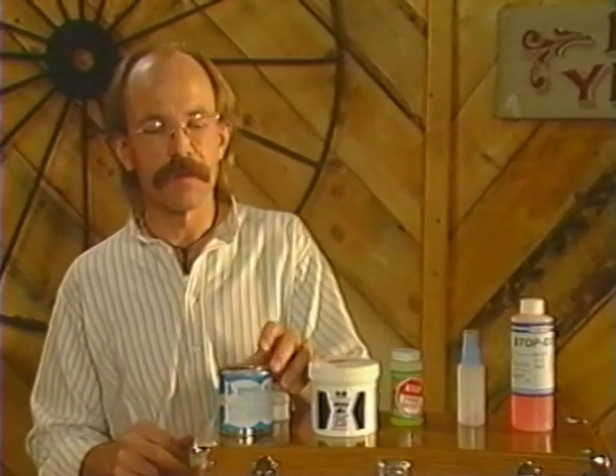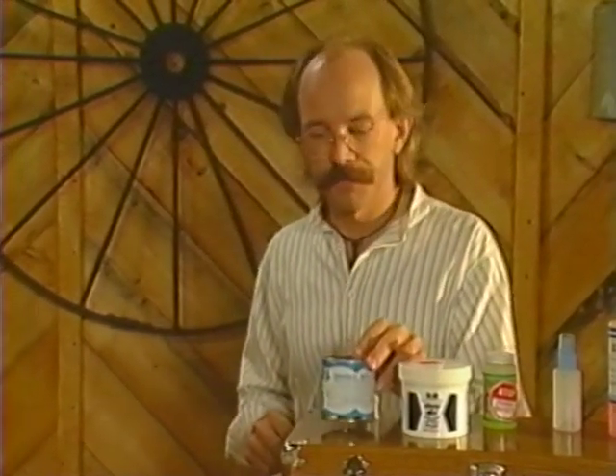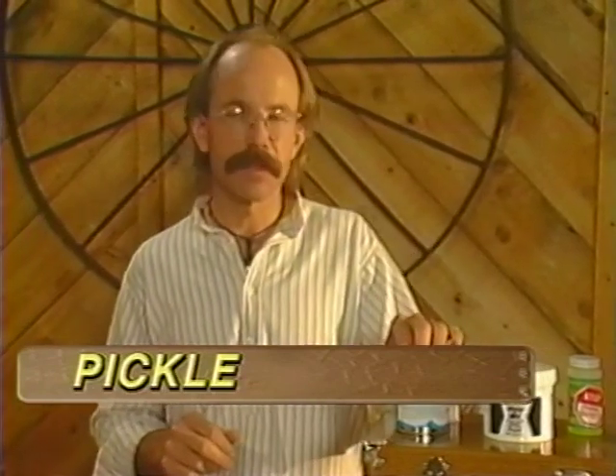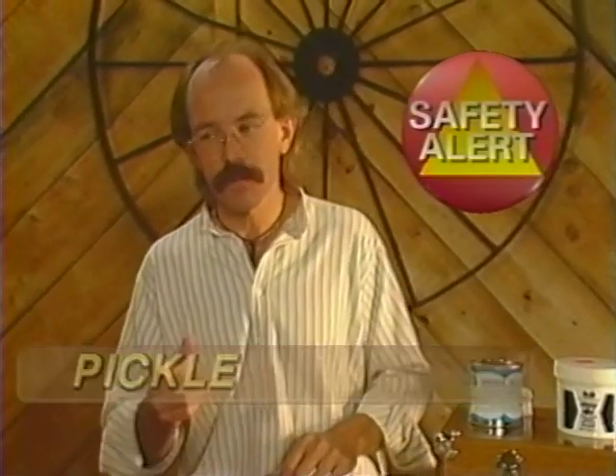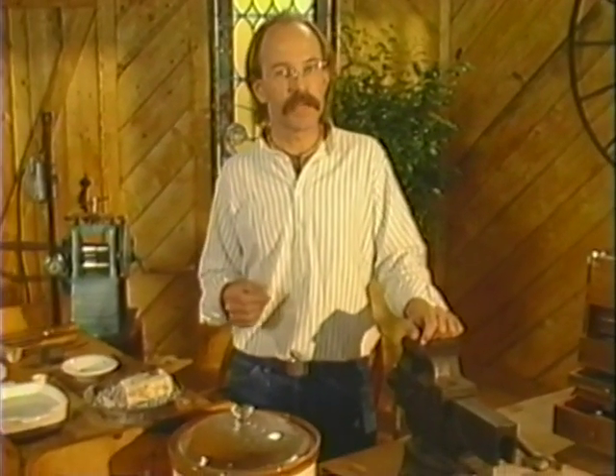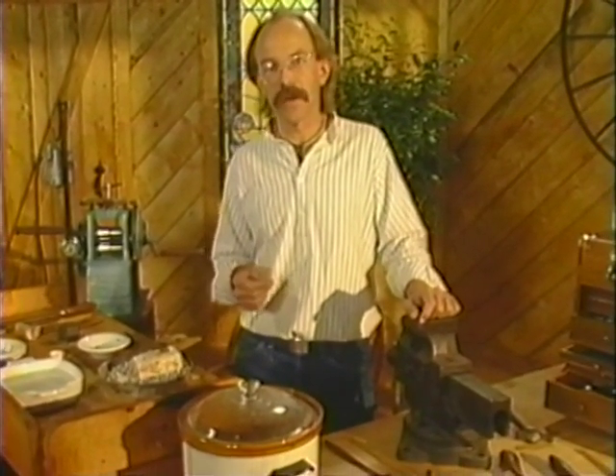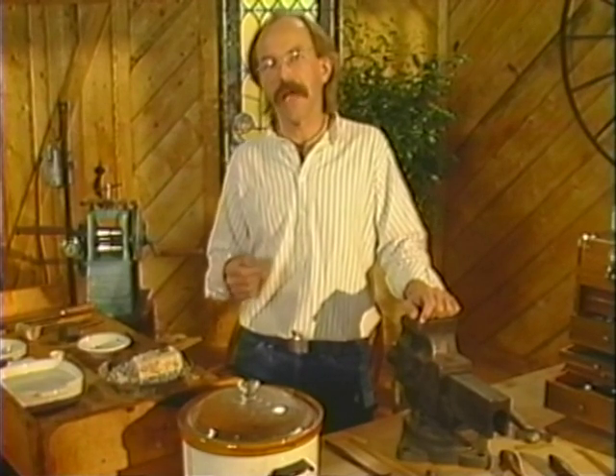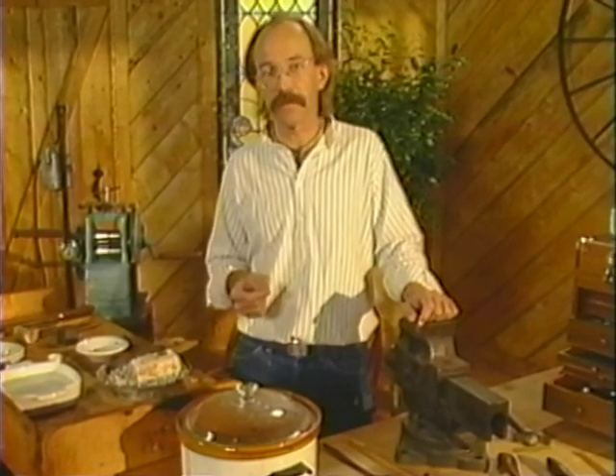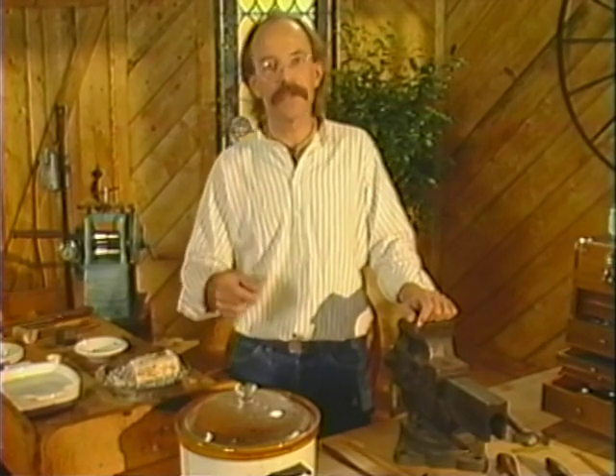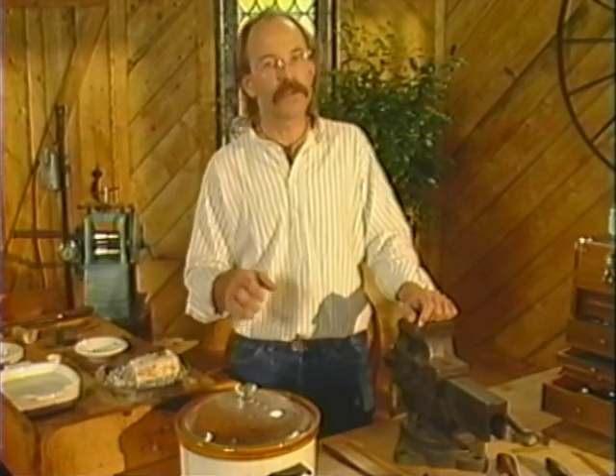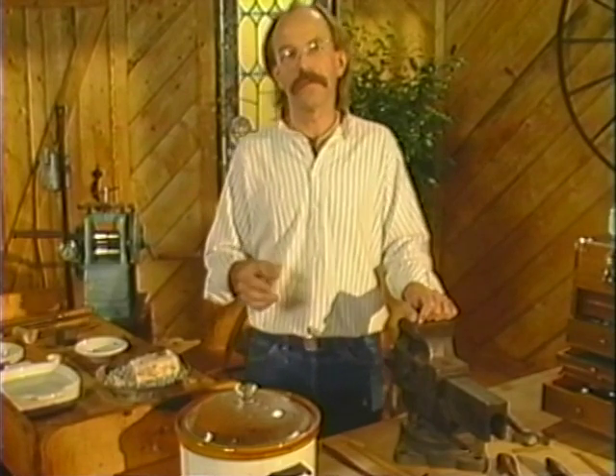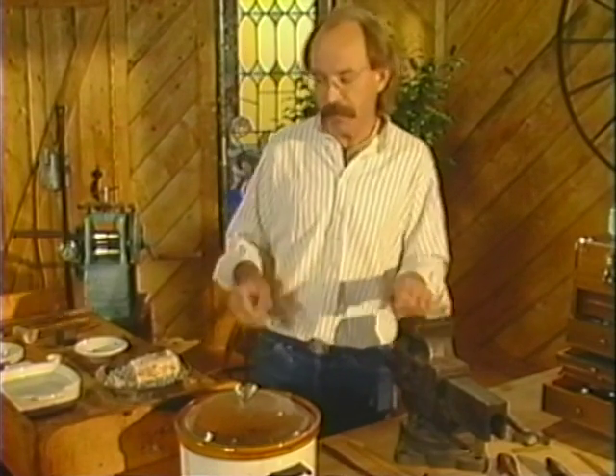Another chemical that's part of the soldering process is called pickle. This is a granular substance that's mixed with water and kept warm at the bench side. During the soldering operation, the metal is covered with oxide film and a flux residue called flux glass. Either of these can be removed by abrasion, but that process is at best tedious and also wasteful of the material. Instead, we'll drop the piece into the pickle, and if the pickle is fresh and warm, after a couple of minutes, both of these surfaces will be removed.